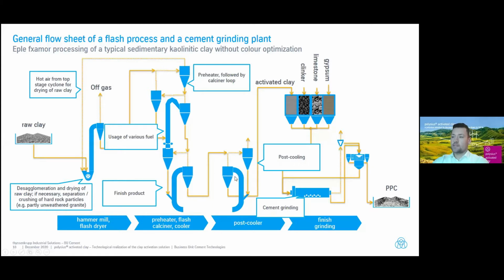Afterwards, we are also having a post-cooling step to bring the temperature down to 80 or 100 degrees C. And also this waste heat here can be used either for the drying here or maybe also for some other purposes. At the end, you are coming up with the activated clay, which can then be ground. So one opportunity would be the intergrinding, meaning you are grinding the activated clay together with clinker, limestone, gypsum. This is possible. Or if you don't want to do it like this, you can also have a separate grinding step, so just grinding the activated clay itself, and then afterwards mixing it to the final cement. This is also possible.